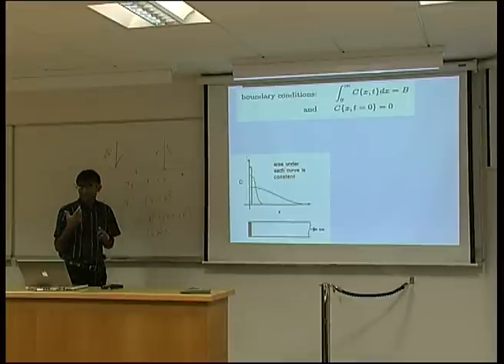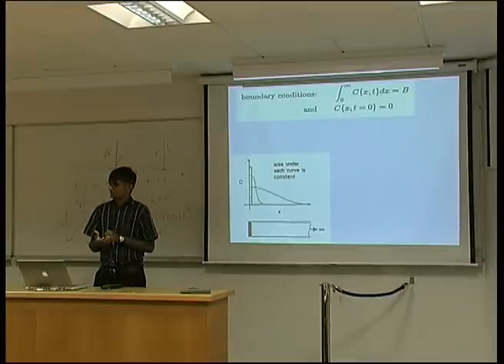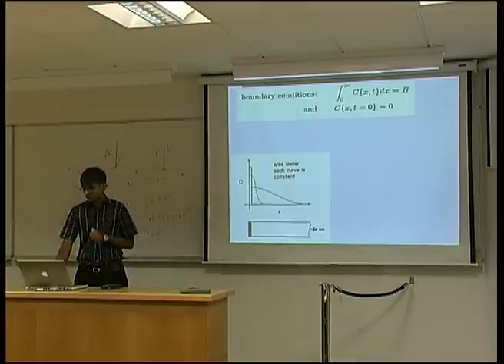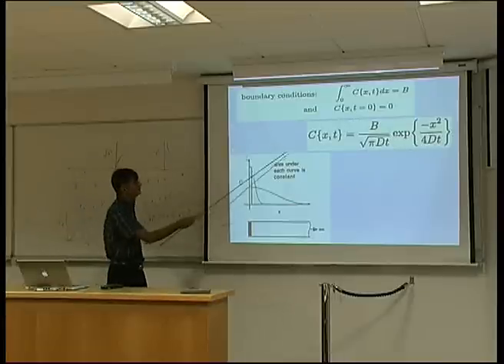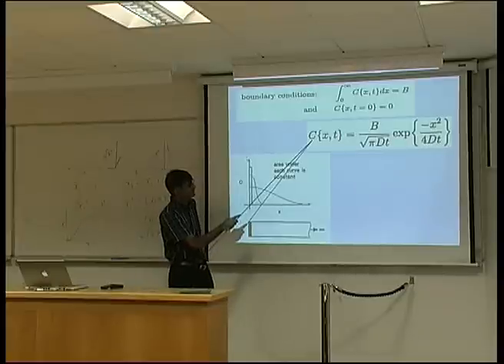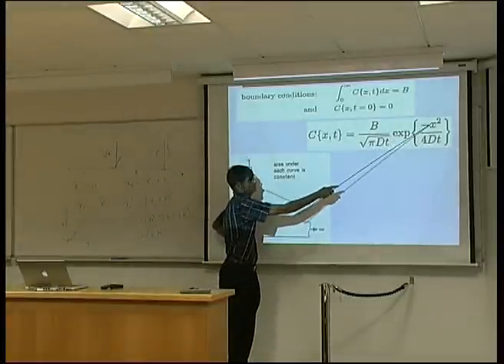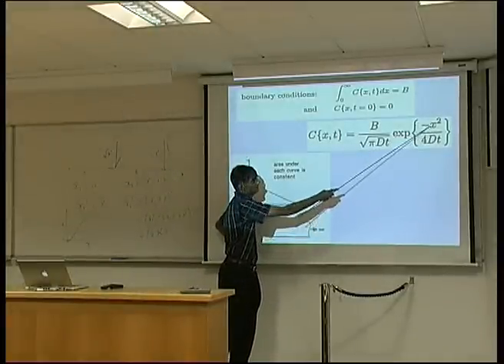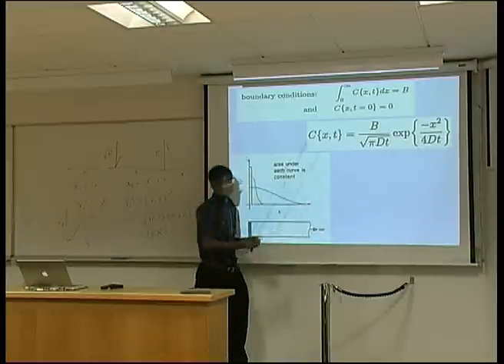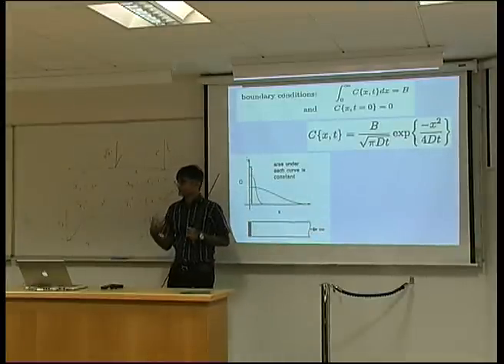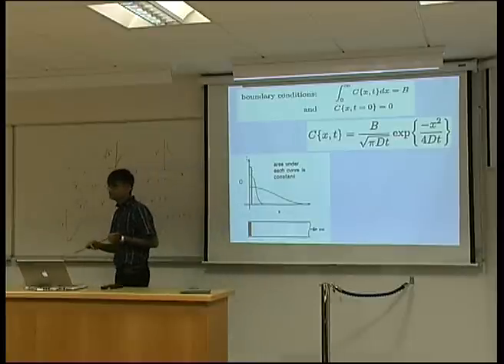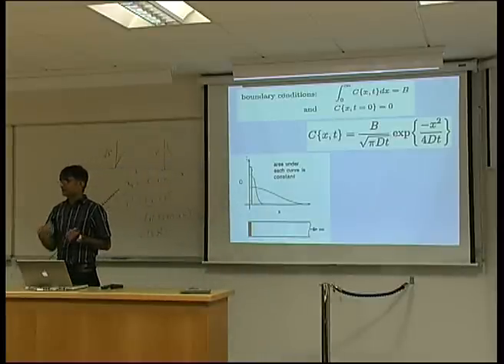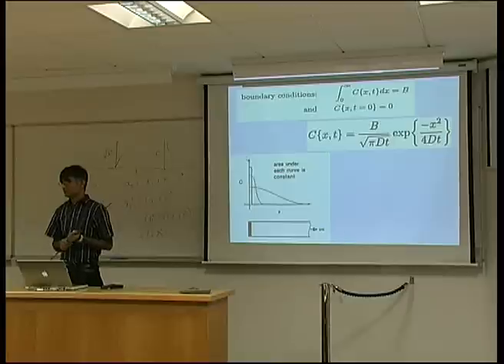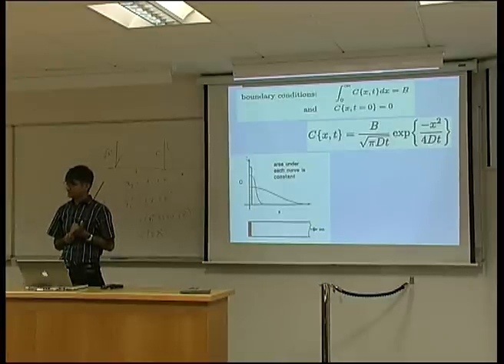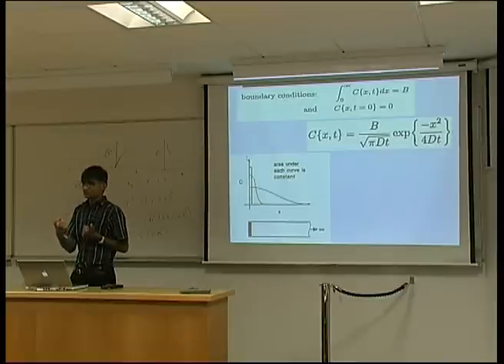And then you try out various functions which would satisfy Fick's law with these boundary conditions, and you find that the concentration varies exponentially with x squared over 4Dt, where x is the distance and D is the diffusion coefficient and t the time. So it's an exponential penetration into your material. Now how do I know that I get this equation if I solve Fick's law with assuming those two boundary conditions? How did I get to this equation?